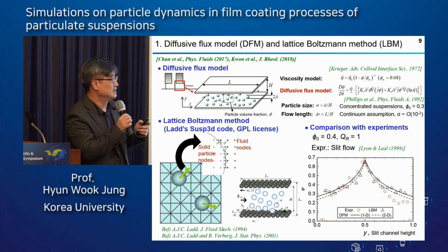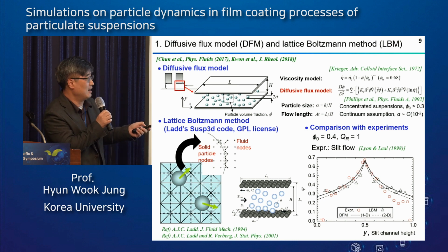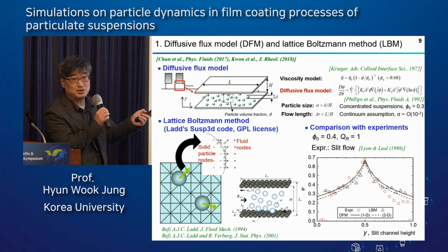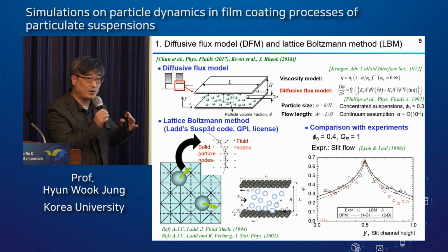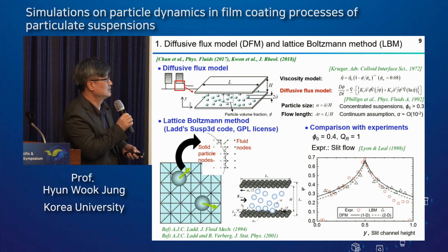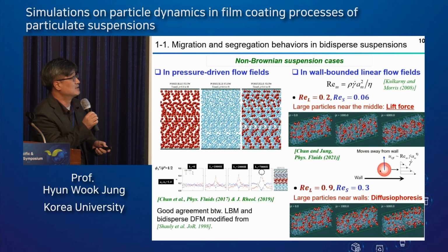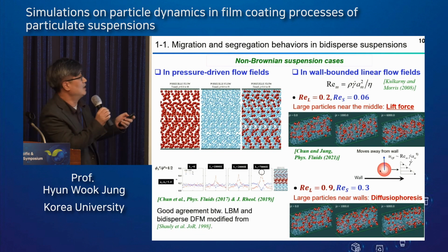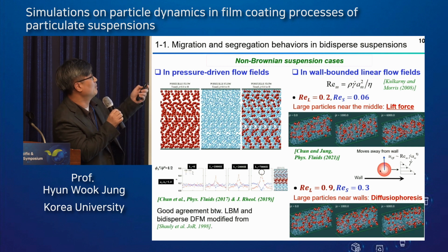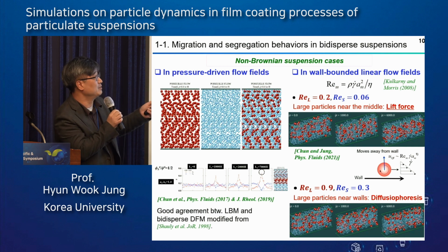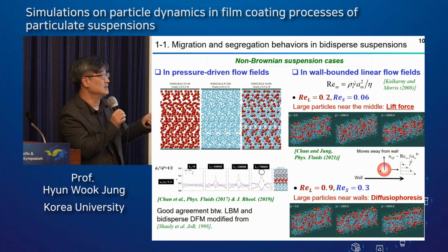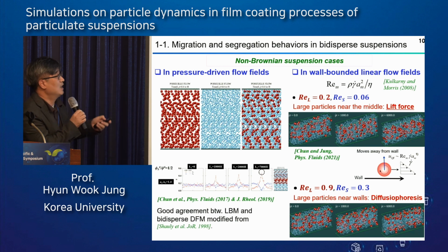So first, we confirmed that our 1D and 2D continuum-based model and the lattice-Boltzmann method well predicted the experimentally observed particle concentration distribution reported by the Leal group in the Poiseuille flow. These are our results. Let me briefly explain some results on the migration and the segregation behavior in bidispersed spherical particle suspensions.